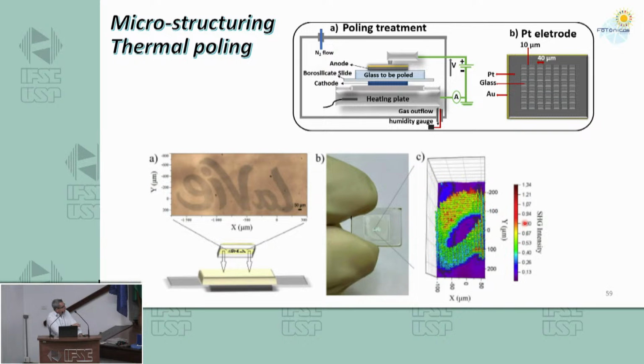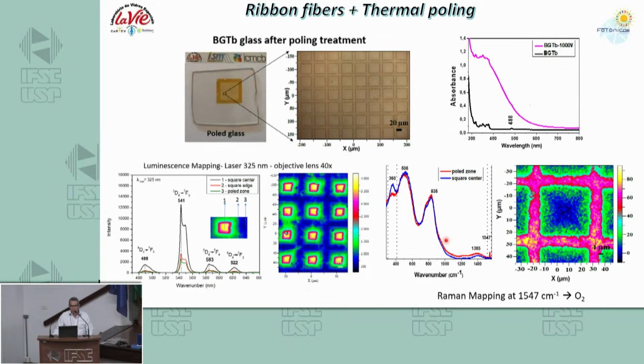second harmonic generation produced in the region where the poling was applied. So there is an increase in the second harmonic generation, and we can use this for some applications too. So this is another interesting thing, that rare earths are known by the stability of the NOx, the number of oxidation of the elements. But using this approach for terbium, we can induce the oxidation from terbium 3 to terbium 4. And this change of the oxidation changed completely the emission spectra.